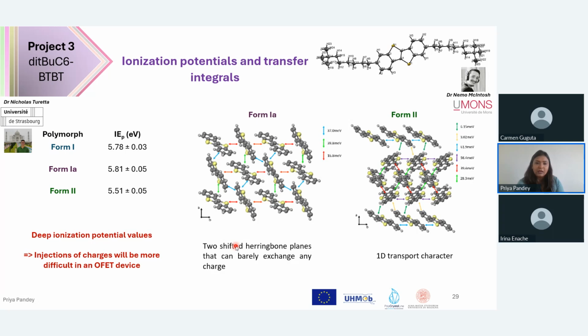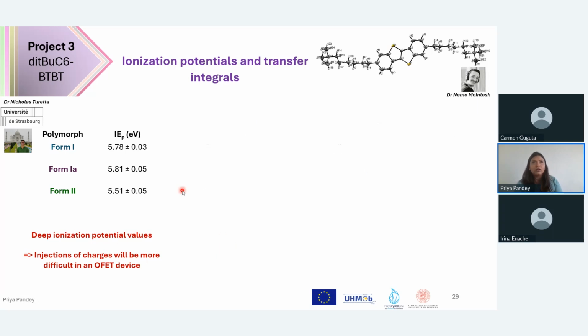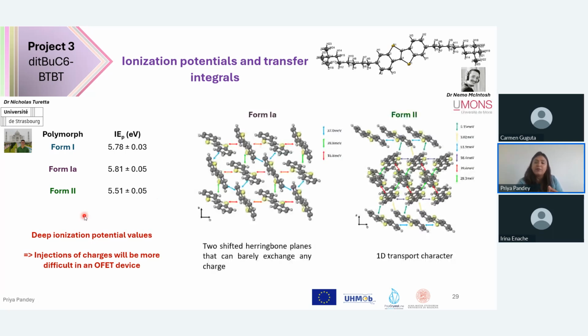One thing we can do to make it better is first solving the problem of isolation of the polymorph, because if we solve that, at least the mobility value will be a bit enhanced, since different polymorphs will have different grain boundaries that hinder the mobility. Then solving the ionization potential values, maybe blending it with TCNQ or other suggestions that people at ICMAB are mainly working on. But until this, I concluded this project because it was almost the end of the PhD.